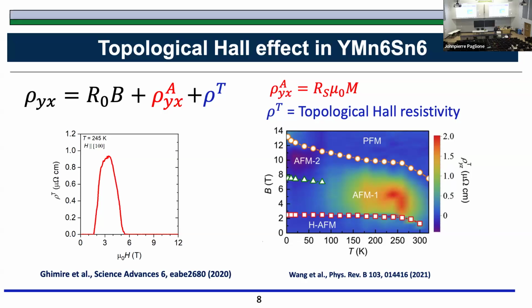So that was something that puzzled us, and therefore identifying the magnetic structure was very important to know why this is happening. Even when we determined the magnetic structure, that magnetic structure itself was not supposed to give this behavior. So there was some theory involved, and what we realized is that, okay, actually temperature is helping it. What temperature does is that it fluctuates the spins, and that particular structure, when fluctuated with temperature, can generate some features, what we call a scalar spin chirality, that can generate this kind of Hall effect. So that was one way.